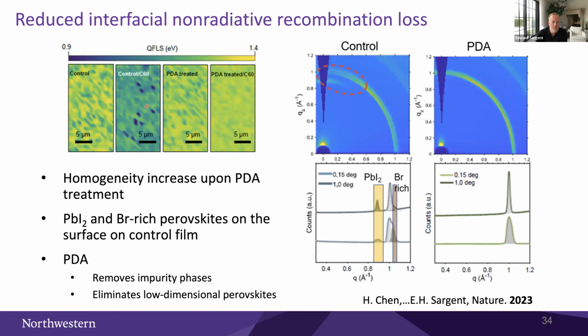This was also reflected in improved spatial homogeneity by doing quasi-Fermi level splitting mapping. We see that the PDA-treated post-C60 surface exhibited indicators of a more promising VOC, based on the amplitude and also based on the uniformity of the quasi-Fermi level splitting data. And it also suggested that PDA can contribute by removing the impurity phases and eliminating the low-dimensional perovskites.